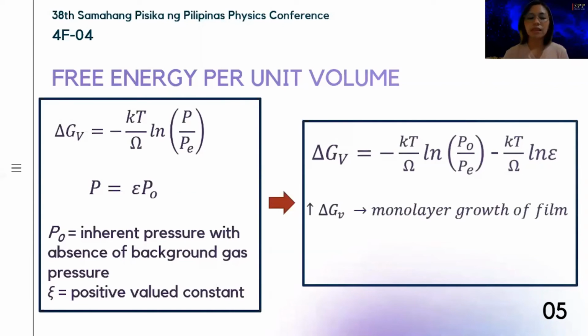An increase in the delta G results in an increase in the total free energy barrier, and this promotes monolayer growth of the film, while a decrease in delta G results in a decrease in the total free energy barrier that leads to either or both nucleation and island growth.